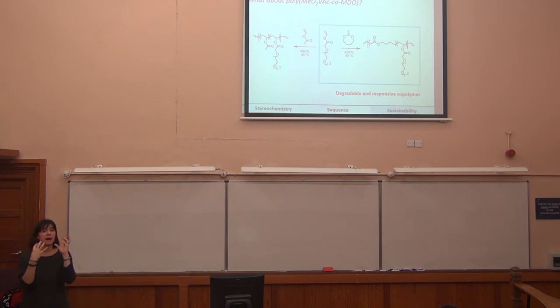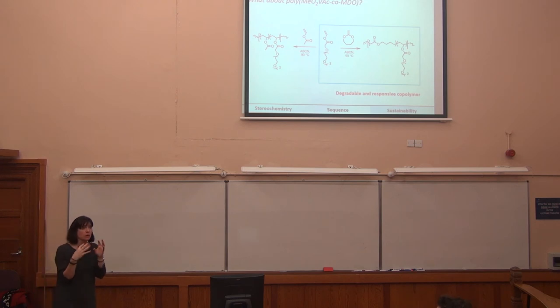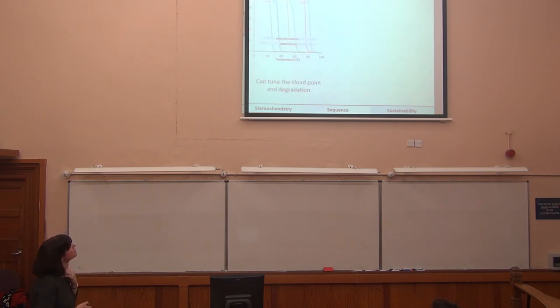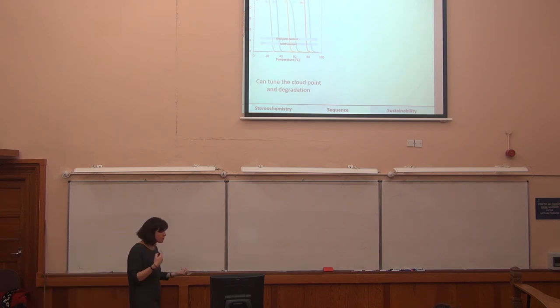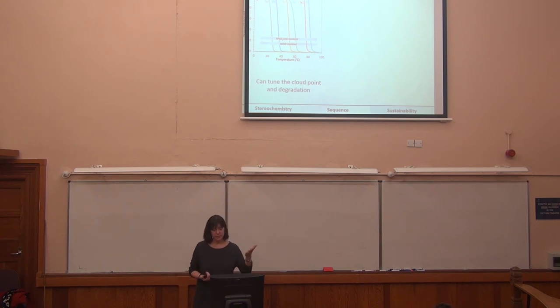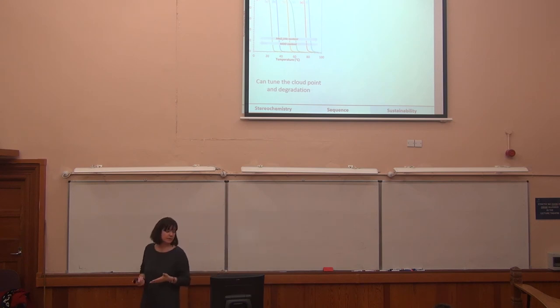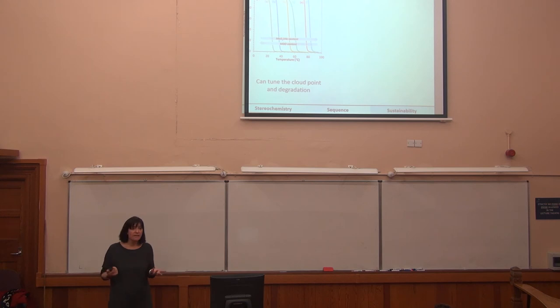And to actually ensure that we had a statistical co-polymerization, we could be very confident in the placement of our ester units through the polymer to allow us to get this responsive and degradable polymer. And I think the cool thing we can do is, by just changing the amount of the two monomers, we tune the cloud points, so we can have something that transitions and potentially could release at 25 degrees or something that releases at 90 degrees. So we can tune this very easily, so we've got a real handle.